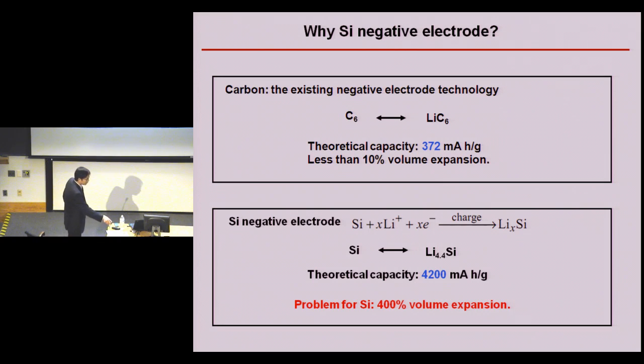But associated with this amazing performance is a huge problem. As you put a lot of lithium into silicon, the silicon will tend to expand in volume. And as you put in 4.4 lithium, the volume change is about 400%. Then when you discharge the battery, you take the lithium away from the silicon, and the structure will shrink back. During this charge and discharge process, the silicon structure will tend to break. That will cause the failure of lithium-ion battery devices based on this material. So even though this material is very attractive, there's a huge challenge here.